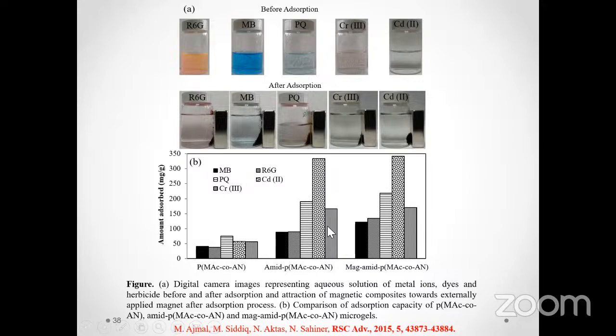And another observation was also that when we have modified these hydrogel systems with the fabrication of these metal nanoparticles, their adsorption capacity was increased. These graph bars are representing the adsorption capacity of my hydrogels containing nitrile groups. And it was observed that when nitrile groups are converted into the amidoxime groups, the adsorption capacity was increased. And when magnetic nanoparticles were prepared, adsorption capacity was again increased. An increase in the adsorption capacity, and an additional advantage of separation of the adsorbent from the reaction medium with the application of an external magnetic field was also observed in this case.